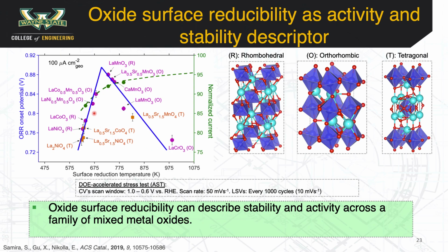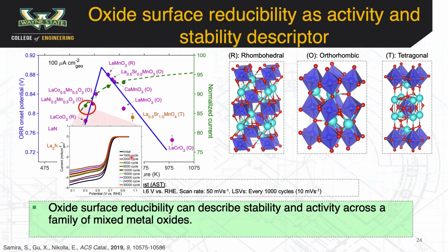In order to validate the hypothesis, we studied the stability of an oxide on the left leg, for instance, LaCoO3, using a DOE suggested accelerated stress test. It is observed that lanthanum cobalt O3 exhibits a significant loss in electrochemical performance over 30,000 cycles of cycling.